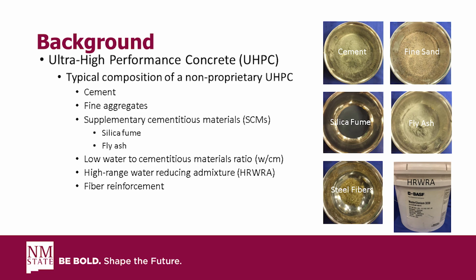Okay. And then the typical composition for the non-proprietary UHPC we developed at New Mexico State University. Of course, what we use is a type I-II cement, shown in the top left photograph there. And then we have our fine aggregates, which is again our fine sand that's passed through a number 4 sieve. And for ours, we oven dry it so it has essentially no moisture in it.